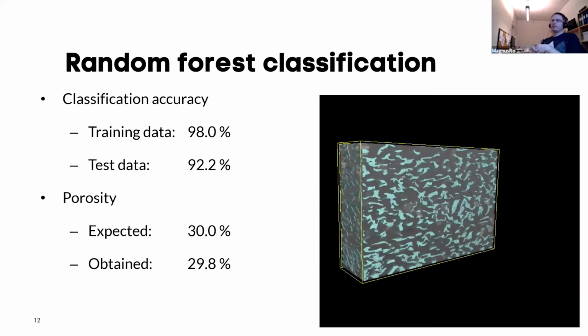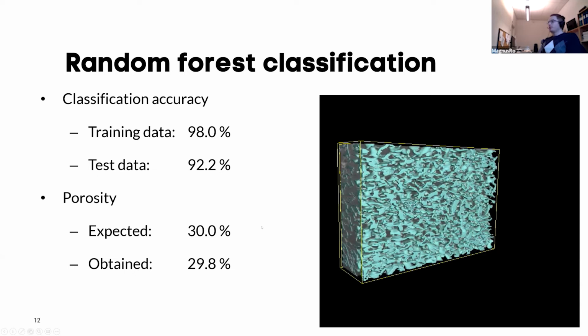So what we get is a pretty decent performance on the test data. We get like 92% accuracy, and the porosity, which is sort of the fundamental of all the geometric properties that we want to get right. We expected it to be 30 because we knew what the material was. We got something very close to it. So it was a very good first iteration, at least, to use random forests.